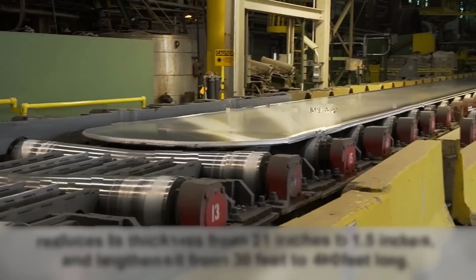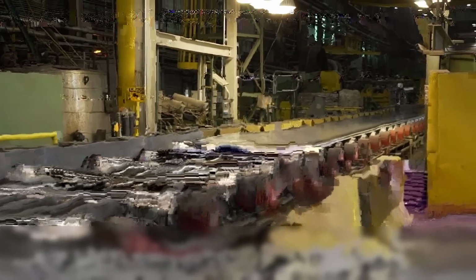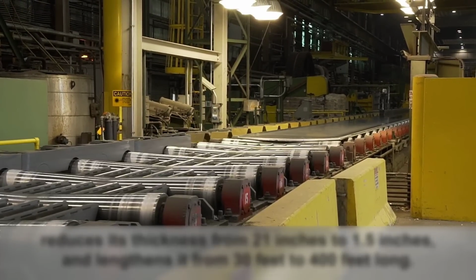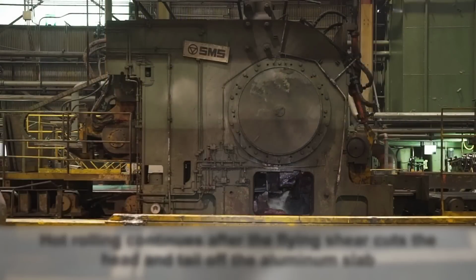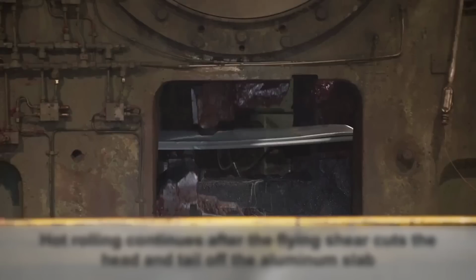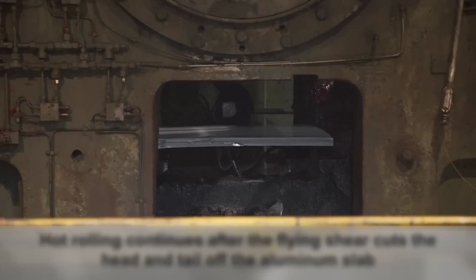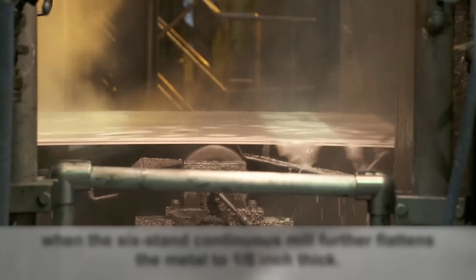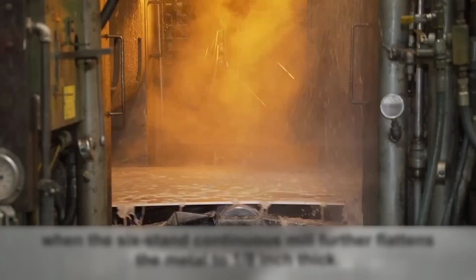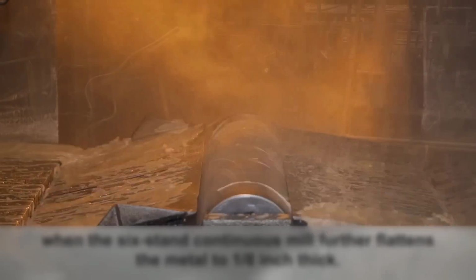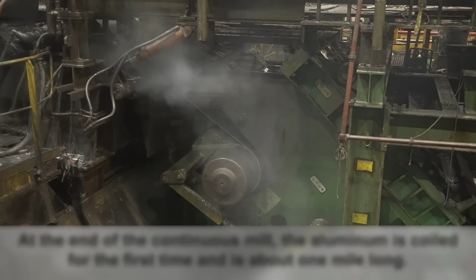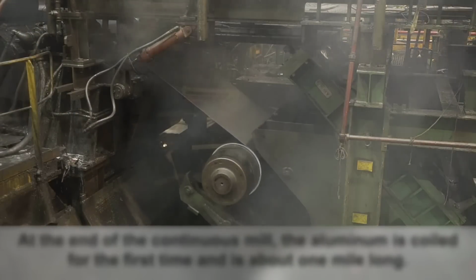Continuing with the hot rolling process, a flying shear severs the head and tail of the aluminum slab, marking the transition to the 6-stand continuous mill. Here, the metal is further flattened, achieving a thickness of 1/8 of an inch. The culmination of this stage sees the aluminum coiled for the first time, resulting in coils that can span up to approximately 1 mile in length.